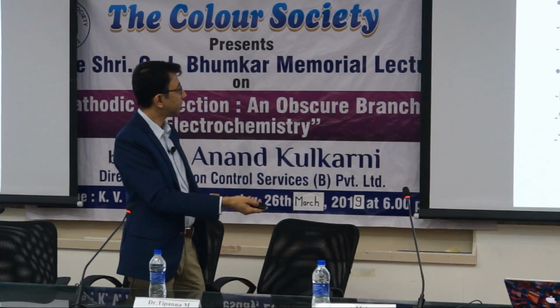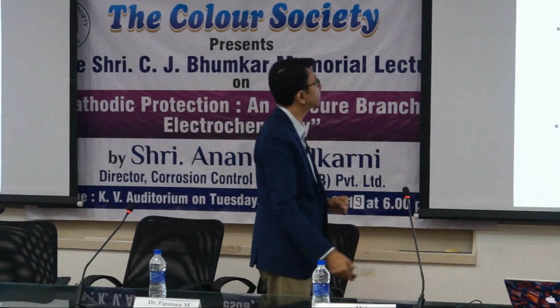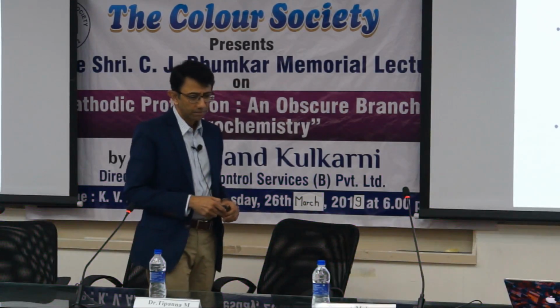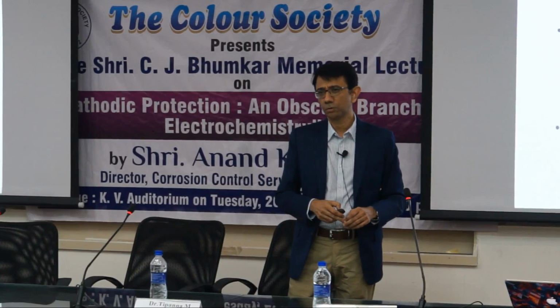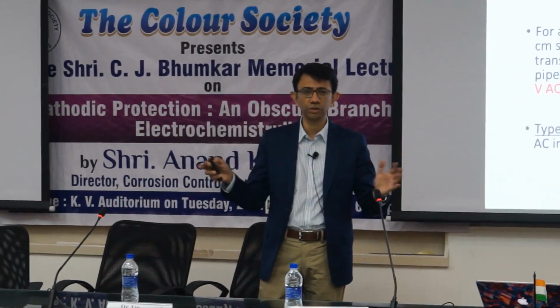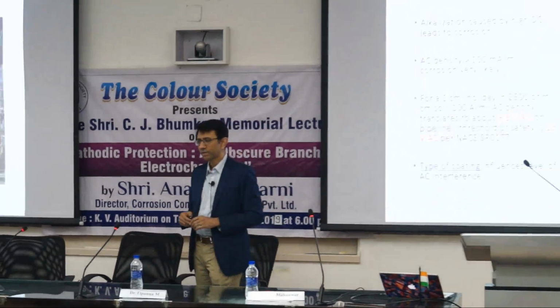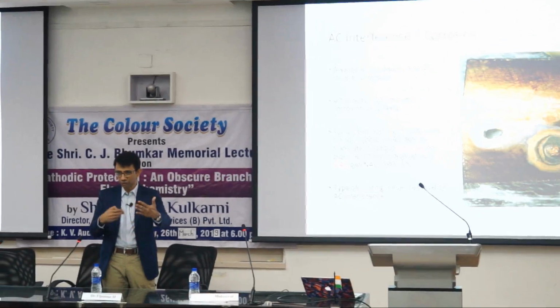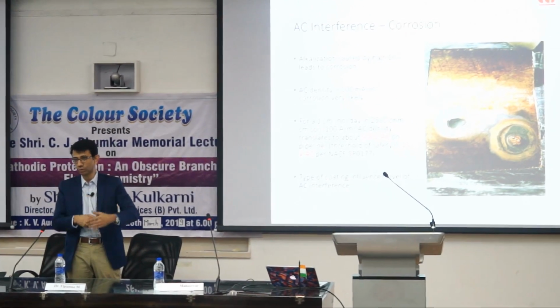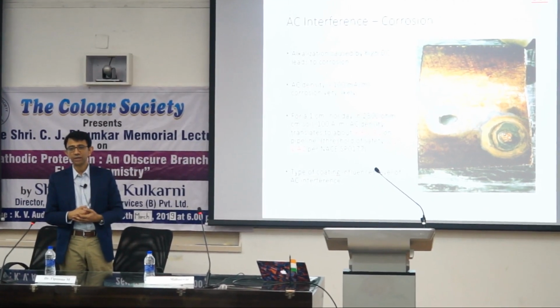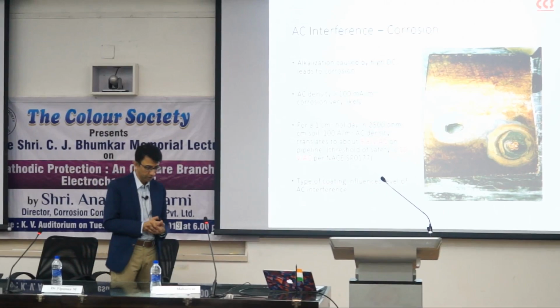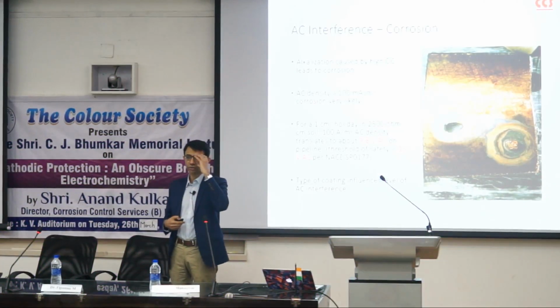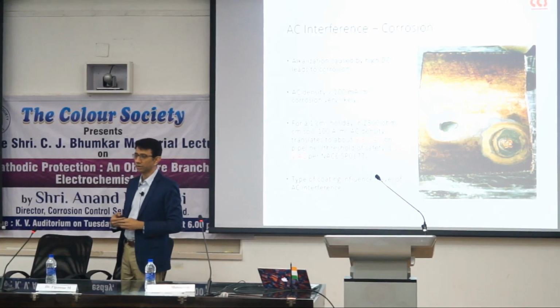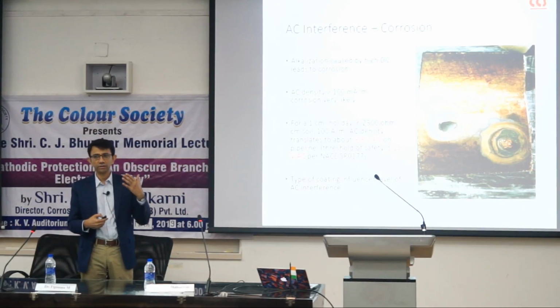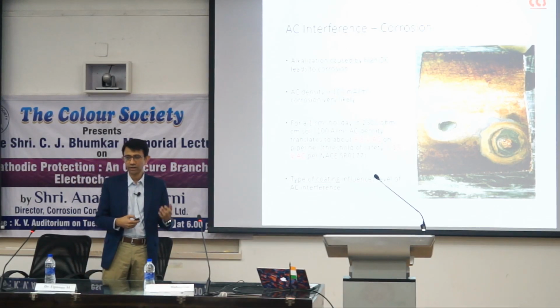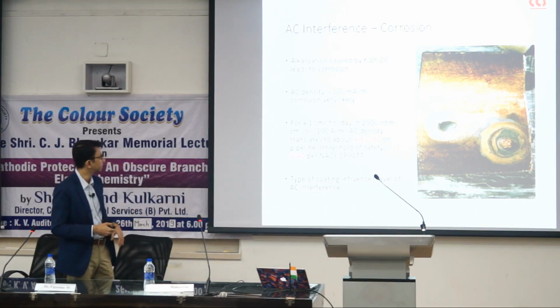I'd like to focus on the next slide, which talks about something even more menacing, which is the AC interference. In early times, there was no problem of AC because we had relatively poorly coated pipelines, coal tar coated pipelines. Their electrical resistance was low, so their electrical isolation from the ground was relatively lower. And so we didn't see very harmful AC potentials on pipes. Today, with high electrical resistance coatings such as polyethylene or fusion bonded epoxy, we find very high alternating current interference. We find very high AC potentials on pipelines.